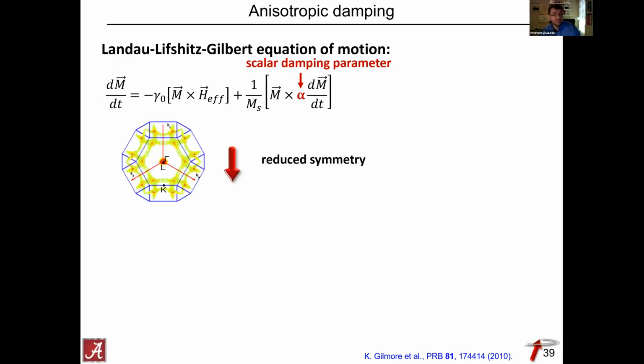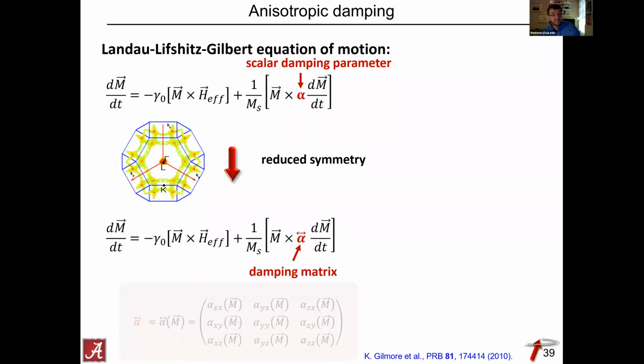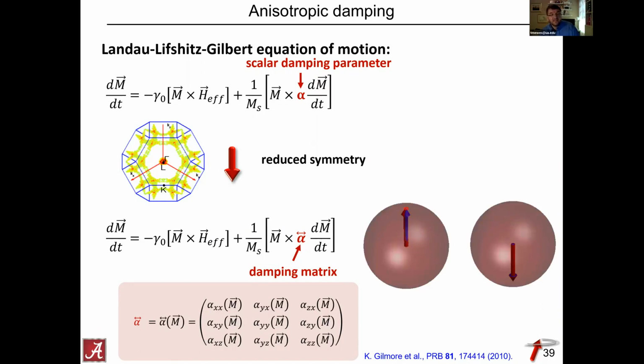we actually know that the reduced symmetry of your system, be it either the crystal symmetry or, like in the case that I showed you, the broken symmetry at the interface, there's actually more to it. And we should rather replace this scalar damping parameter with a damping matrix, where you can actually have different contributions to that anisotropy of the damping, where one just having these different entries would be the so-called rotational anisotropy, and the other one where the entries themselves depend on the magnetization. These are called orientational anisotropy of the damping. And so with that, what you get then is a damping that can be very different along different orientations of your crystal or your system, if you look at a bilayer system like we did here.